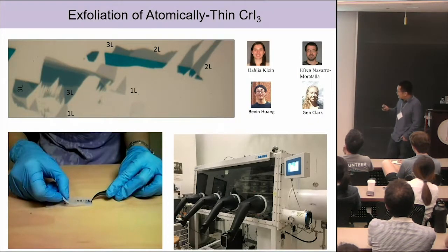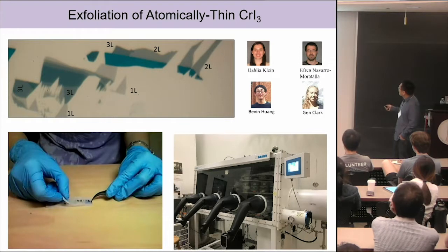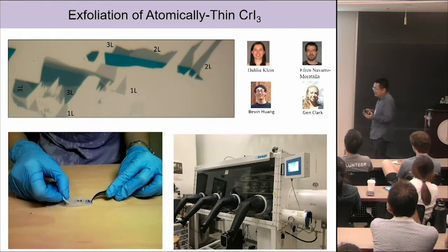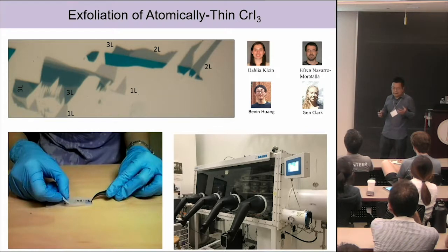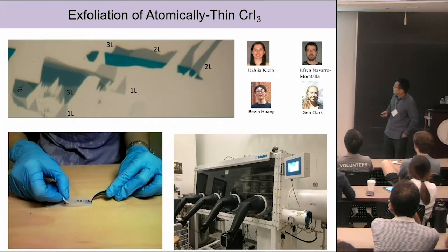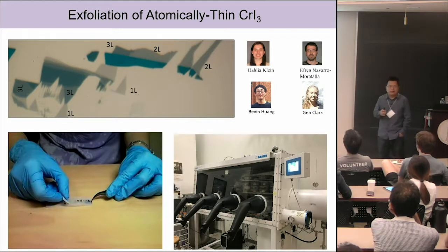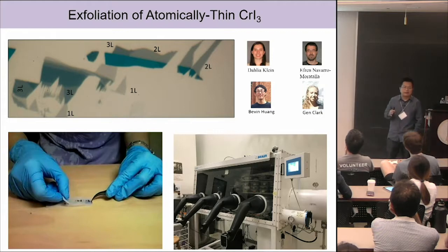So initially, we also worked with Pablo's group, and actually tried to get these monolayers. These 2D magnets are easily exfoliated, but they're also not stable in ambient conditions. So we work with all these in a glove box, and here I just show you an optical microscope image of the samples. Just by optical contrast, you can already see 1 layer, 2 layers, 3 layers, etc. So it's quite easy to exfoliate. The only challenge is that it's just not stable in ambient conditions.